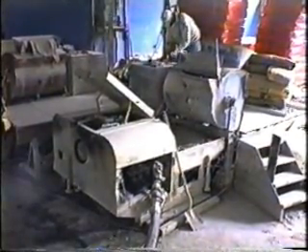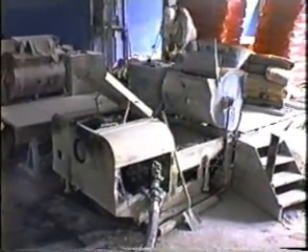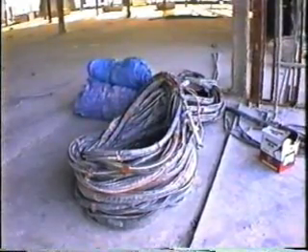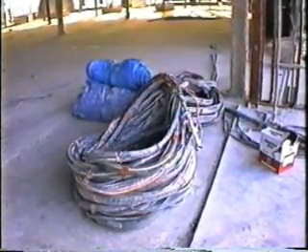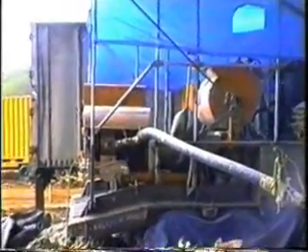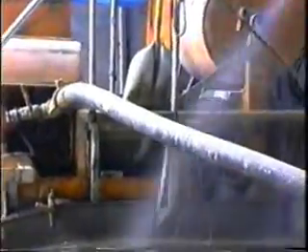Rotor-stator pumps can be and are typically used for lower production rate jobs and where equipment must be located on the floor to be sprayed. The material hose should be reinforced smooth interior vulcanized rubber as used in the plastering industry. Total hose length should not exceed 335 feet for piston pumps and 100 to 200 feet for rotor-stator pumps depending